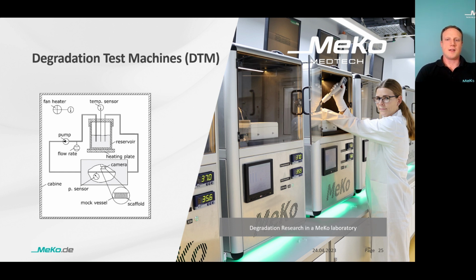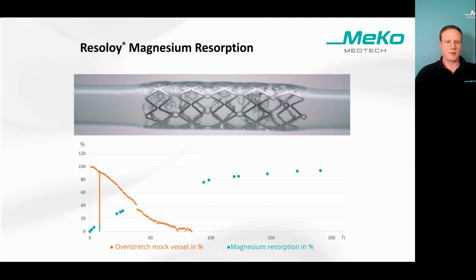The ambient air and the SBF are heated to 36 to 37 degrees Celsius, and the flow is measured. A camera takes images of the stent during degradation, and these images are stitched together to generate a time-lapse video. Additionally to the video, the magnesium ions in the fluid are measured photometrically, and the mock vessel diameter is tracked during degradation to track the loss of radial force of the stent. The following video shows a degrading scaffold and the corresponding degradation and loss of radial force curves. I will stop the video and go back to explain a little bit how it works.